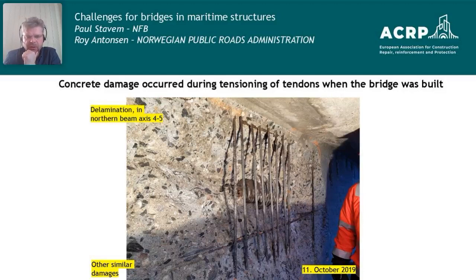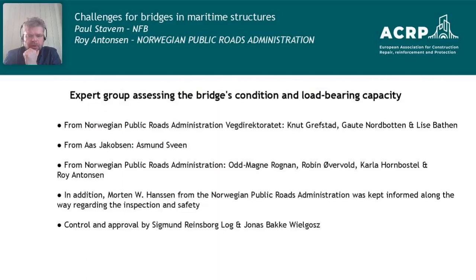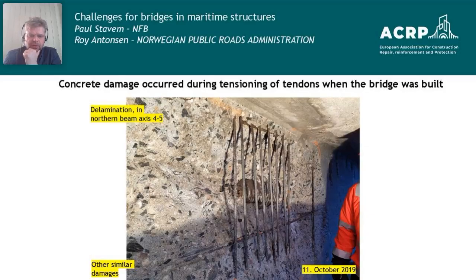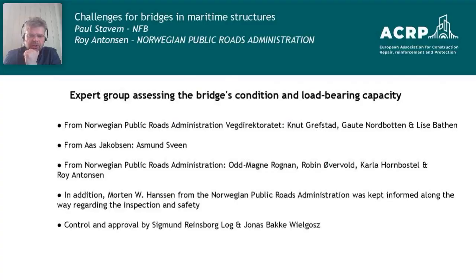And we also saw that this steel joint here is supposed to be grouted. And grouted means that you inject a cementitious mass inside of the ducts and the joints, and this cementitious mass is called grouting, and it's supposed to protect the tendons inside from corrosion, right? And we saw that this joint here was empty. It was not properly injected. So because of this, we had to get assistance from other people in Statens vegvesen, the Norwegian Public Roads Administration. And for those interested in looking at these names, they are all listed here. You can do that afterwards if you want.